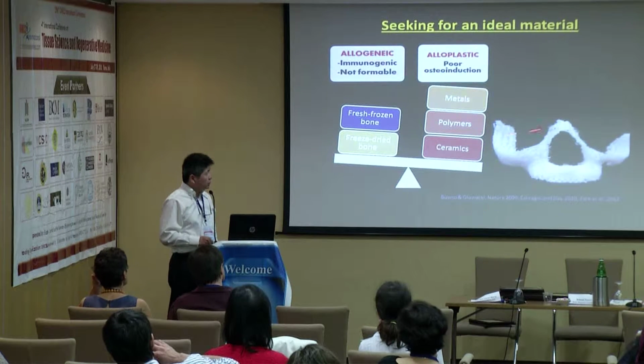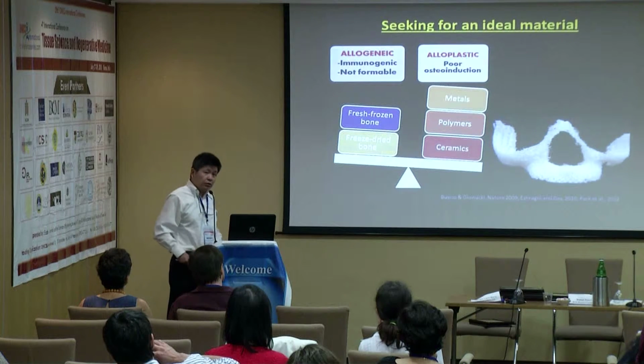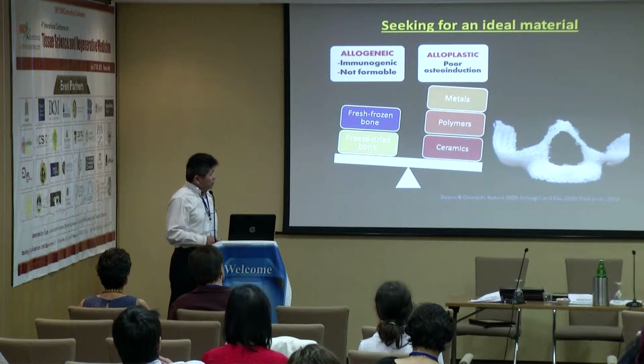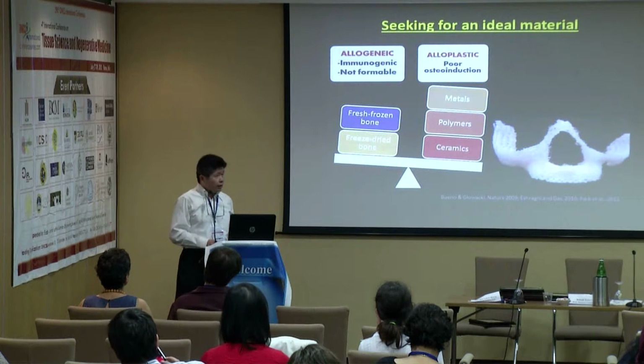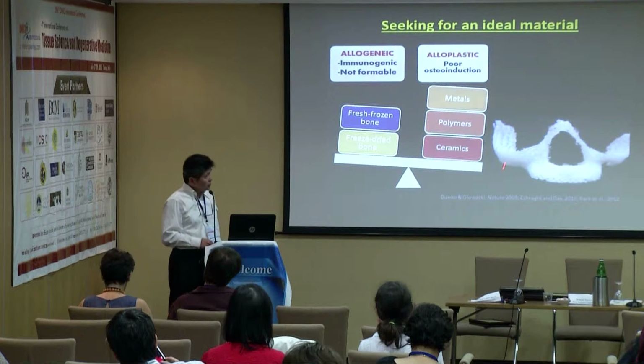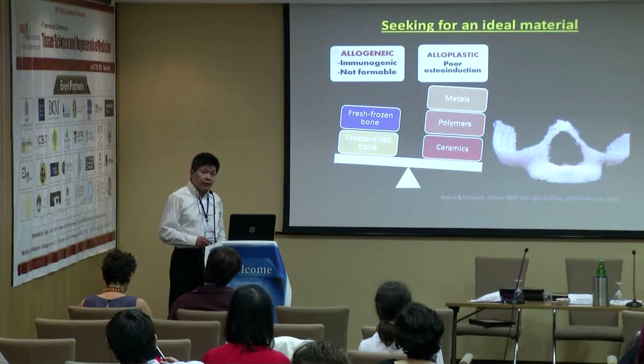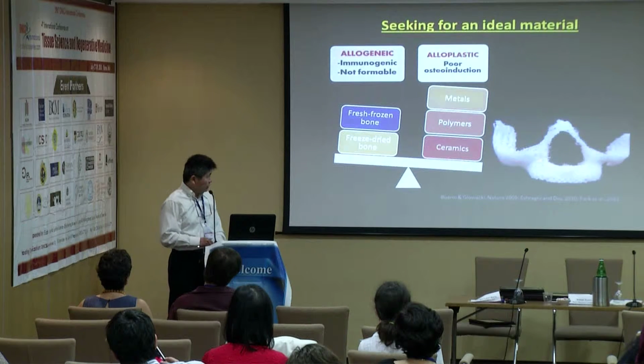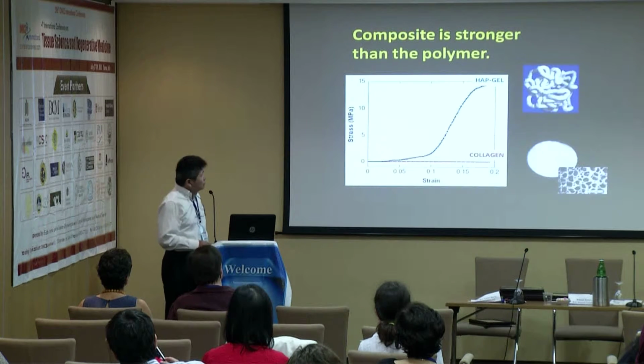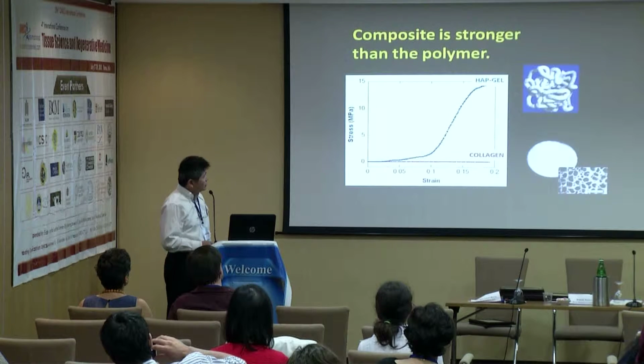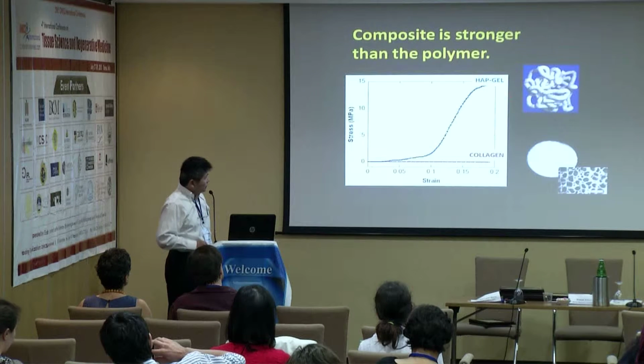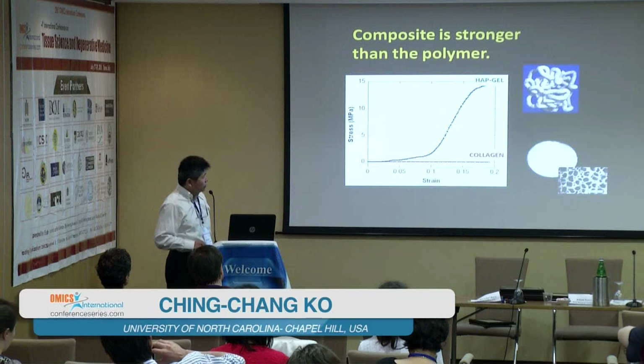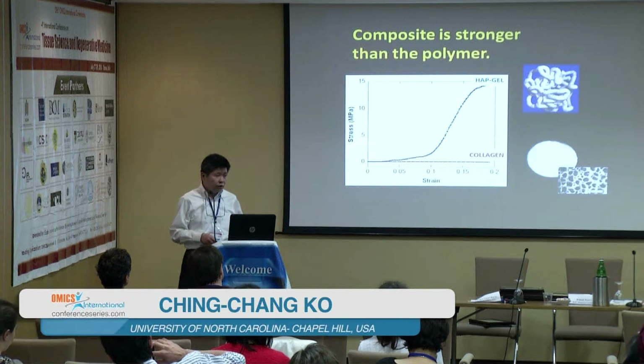Polymer materials create a lot of very nice detailed microstructures, even nanostructures. However, in personal communication with the NIH folks, it's a little frustrating at this moment because the material itself is not strong enough. Although there are a lot of beautiful publications, the translational value is still very limited. So we still have to look for composite materials. Here is one example of ours. We're using a hydroxyapatite-gelatin composite, creating a porous structure, and if you compress this material, you get a loading curve like this. But if you take collagen and compress it, you get this number, which means there's not enough stiffness to support the loading.